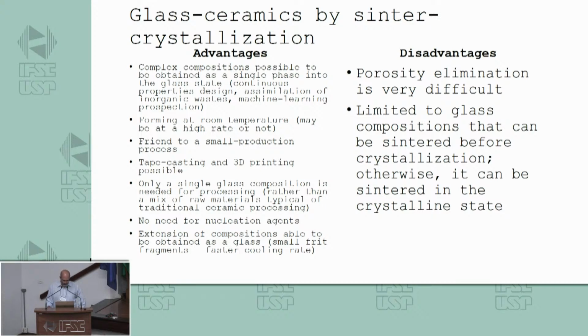And in terms of compositions, it's possible to extend them in the sense that the glass that you have to produce is not a bulky glass or a volumetric piece of glass. You can make small fragments, with very fast cooling, for example, between cylinders, or pouring the glass in the water, so you have a much higher cooling rate. And then you can get a glass from not very good glass formers, which increases the range of compositions that you are able to use now.